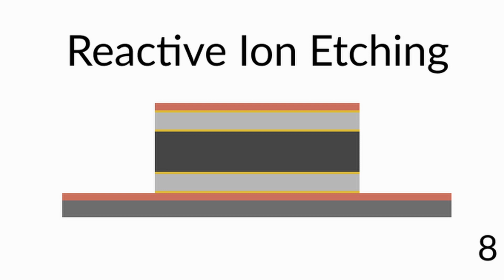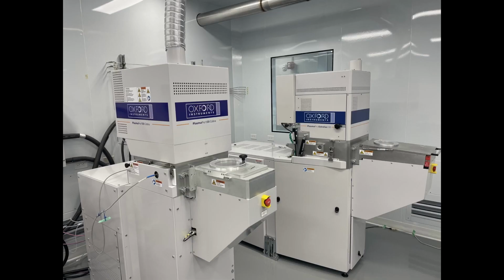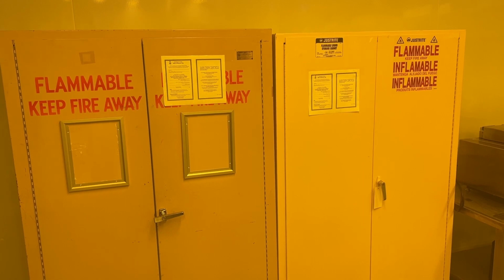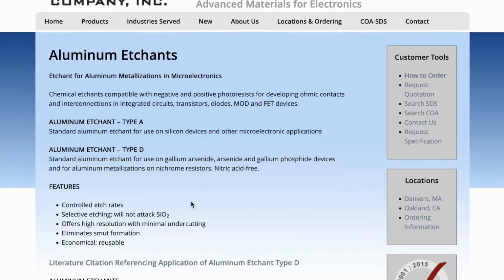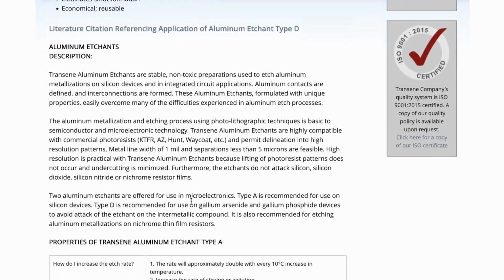And originally, I was planning to do dry etching with reactive ion etching of both the aluminum and PDMS layers, but actually the reactive ion etching machine at TNFC doesn't have the power to do aluminum dry etch. So instead, I was going to do aluminum wet etching, but when I went to start the process, we thought that we had some aluminum wet etchant at TNFC, but it turns out that we ran out recently. So I had to order some from Transene, and it should be arriving next week.